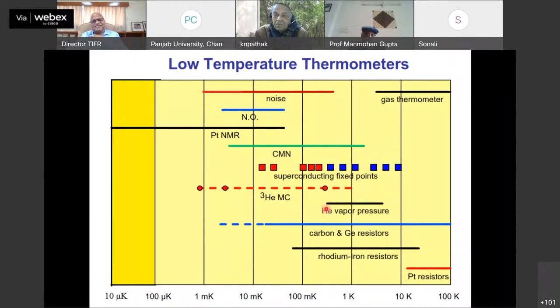We need a reliable sensor to measure it, and most of the sensors which work at fairly higher temperatures, let's say 4K to 100K, will not work at low temperature. The best one is known as the noise thermometer. The other one is the platinum NMR, which works down to about 10 microkelvin. So use the nuclear susceptibility measured from NMR to measure its temperature, and the noise, which is ubiquitous in every resistor, can be used as a measuring sensor.